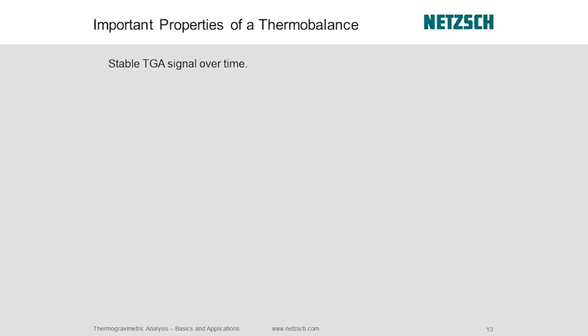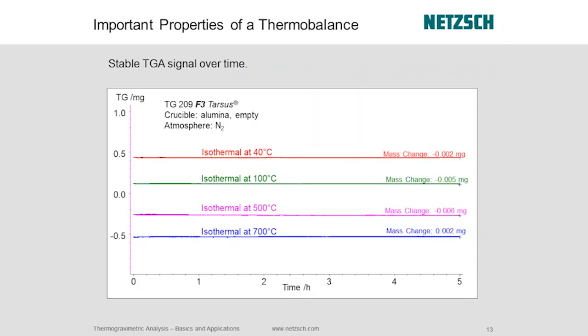First of all, we want a stable TGA signal over time. Okay, so here's a good example of our system. This was the one I mentioned at the beginning, the basic TGA instrument called the TG209F3. That's kind of our bread and butter TGA up to 1,000 degrees C. And you can see even with the basic system, we're holding isothermally for 5 hours at three different temperatures under nitrogen with the empty alumina ceramic crucible. And you can see that it's essentially extremely stable.